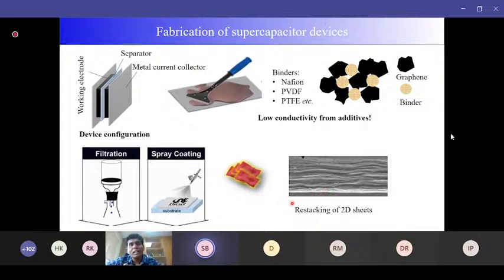But in this case, although this is a binder free sample, so there is no problem from the insulating binders, those sheets are very compactly arranged, as you can see from the cross-sectional SEM image. So whenever the electrolyte ions want to access, they can access mostly the outer surfaces. They cannot go inside. Our main target was to use nanomaterials to access the surfaces, but due to this restacking, we cannot access the intermediate layers. So the main purpose of using the nanomaterials is gone here.